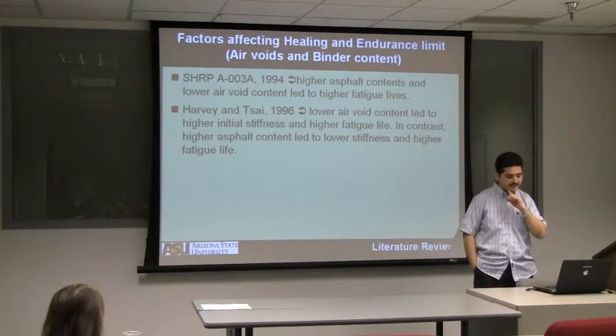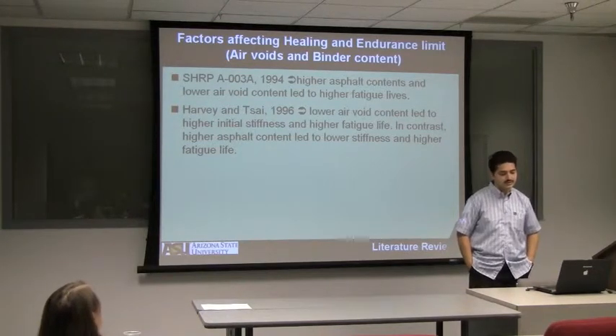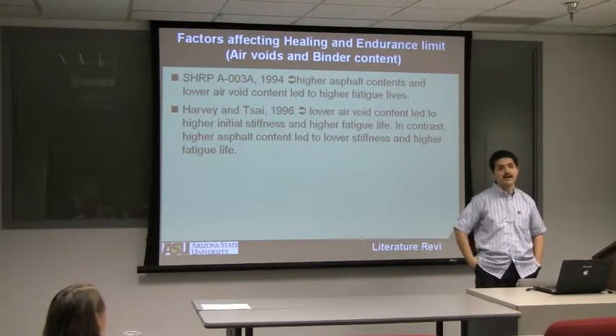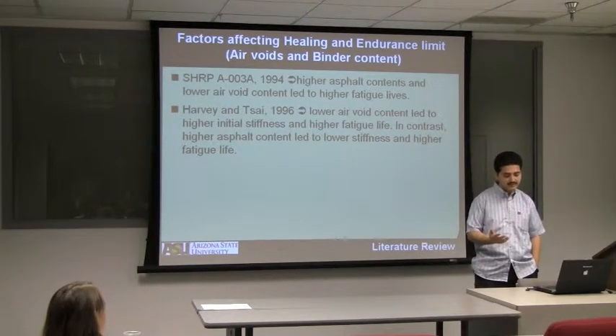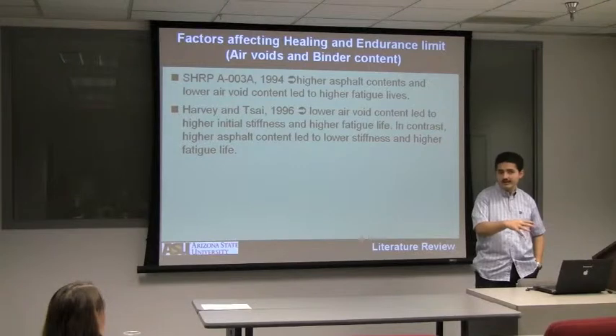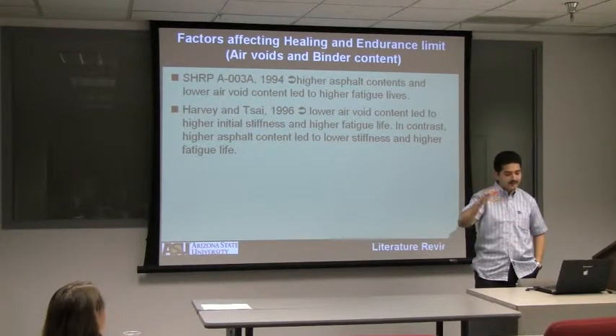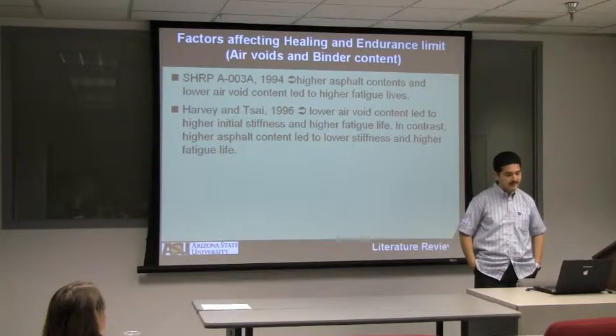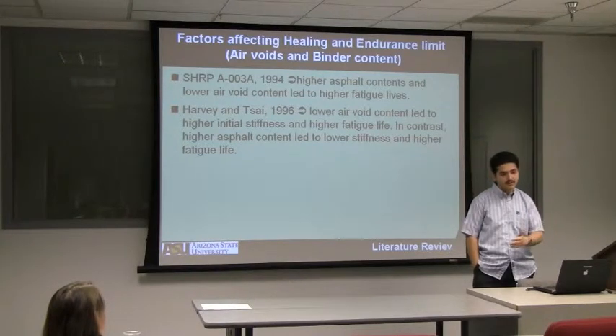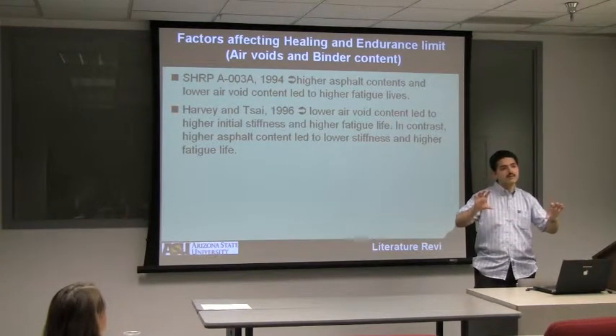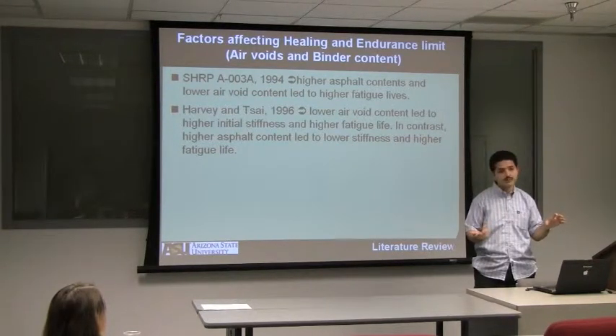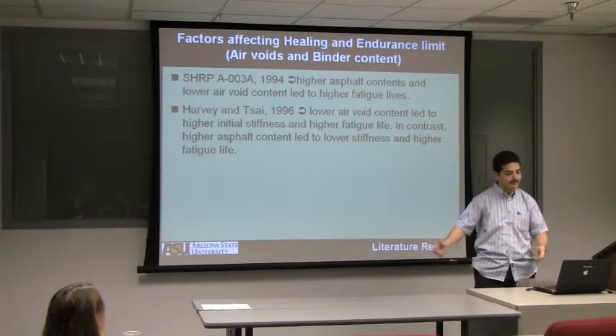Another project was done by Harvey and Tsai in 1996. They mentioned that a lower air void content will lead to a higher initial stiffness and a higher stiffness fatigue life. On the other hand, once you decrease the binder content, this will have a lower fatigue life. So here, as you can see, in contrast, higher asphalt content gives lower stiffness but higher fatigue life. Once you increase the viscous part or the flexible part, which is the asphalt, the material will be more flexible and it's going to take much longer to fail.